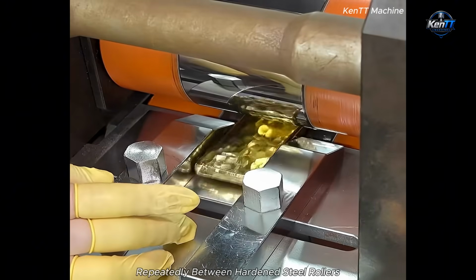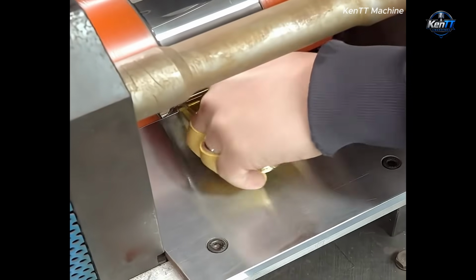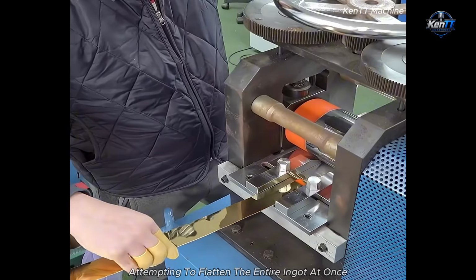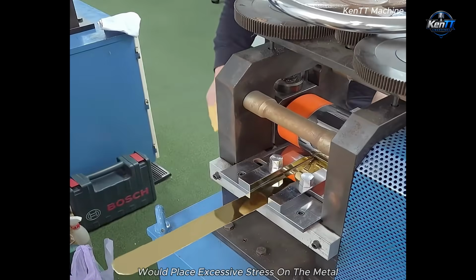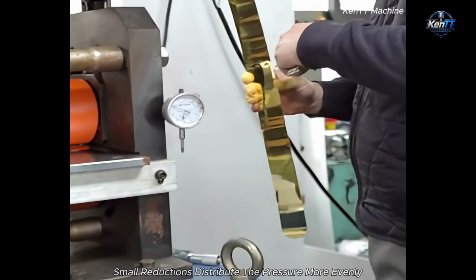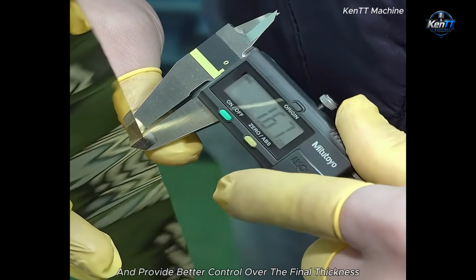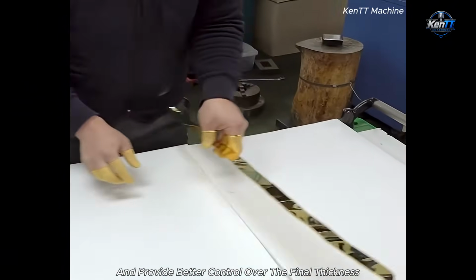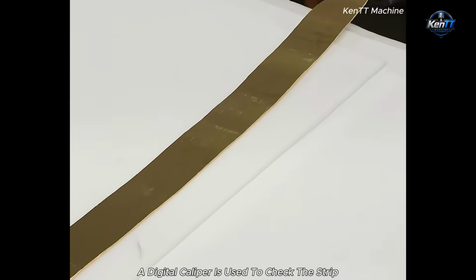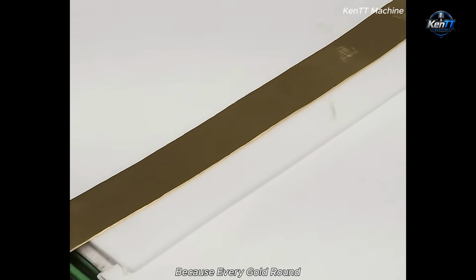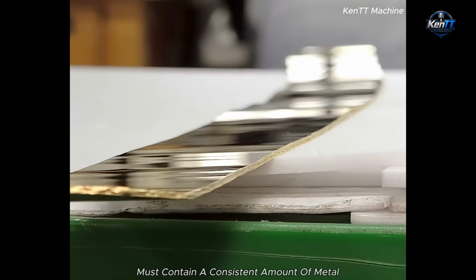The bar passes repeatedly between hardened steel rollers. The gap is reduced gradually, making the gold longer and thinner with every pass. Attempting to flatten the entire ingot at once would place excessive stress on the metal and could produce deep cracks. Small reductions distribute the pressure more evenly and provide better control over the final thickness. A digital caliper is used to check the strip because every gold round must contain a consistent amount of metal.